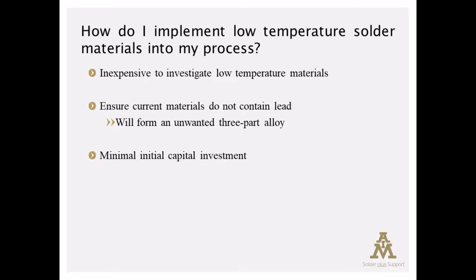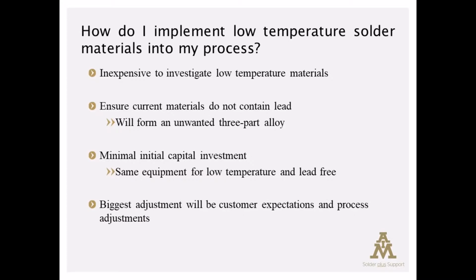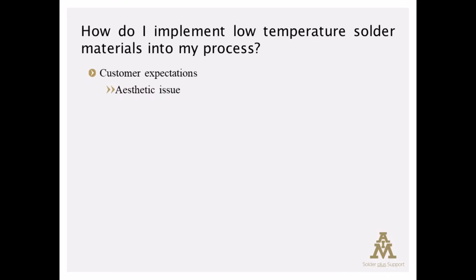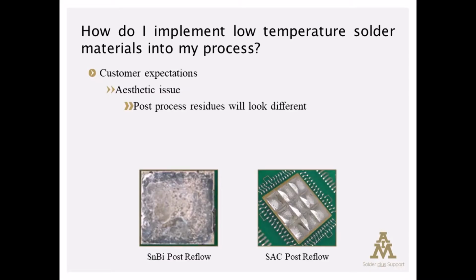We won't have the capital investment that we had when we transitioned from leaded solder to lead-free solder. All of the equipment that's lead-free capable is also low temperature capable. When we transitioned from leaded to lead-free, new ovens had to be purchased in order to accommodate the higher peak reflow temperatures. New wave solder equipment had to be purchased to accommodate the degradation of the innards of the equipment by virtue of contact with the molten lead-free material. And so those things won't have to take place. The biggest issues will probably have to do with customer expectations and process adjustments. So for example, the aesthetics of the low temperature material will be different than the material that is currently in use. The residues can look different. So there are those accommodations that need to be considered.